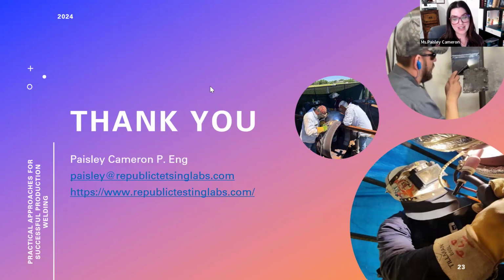I've done a lot of R&D myself on 5 chrome in particular. The reason is that in our FCC reactors, we use a lot of 5 chrome on the bottom section of the cones, and they go through a lot of repair. There isn't a specific outline that I'm privy to at this moment. There may or may not be requirements, but we found with our welders on our aged material, we use artificially aged and we use some actual aged material that we were comfortable with. 5 times was our case where we would go through it and not re-weld on 5 chrome in particular.